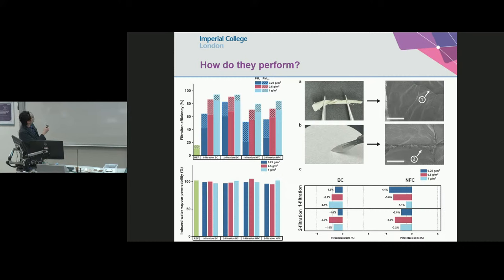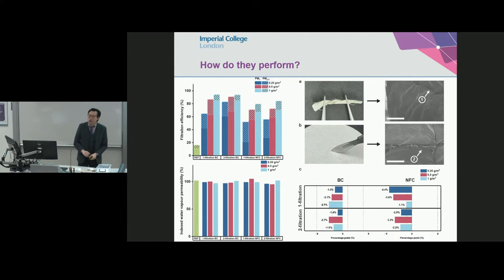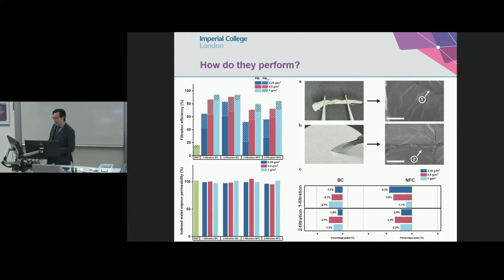For those coated samples, you can easily hit 90%, nearly 95% of filtration efficiency for particles less than 2.5 microns, with just 1 gram for every square meter of your fabric being coated with that. What really makes us excited was that the water vapor permeability, again, uncoated sample versus those coated samples, stayed the same. Again, it's because the coating is so thin, and secondly, cellulose being cellulose, those hydroxyl groups that you have seen earlier, they are rather hygroscopic. So water will permeate through whatever cellulose layer that you put on quite happily.